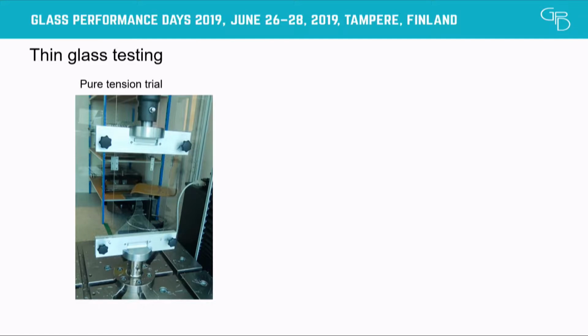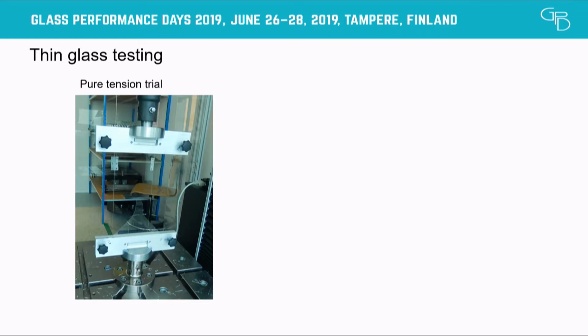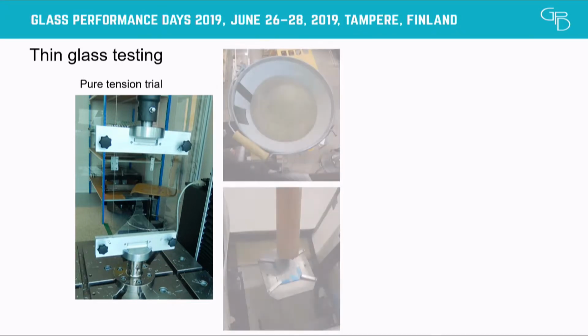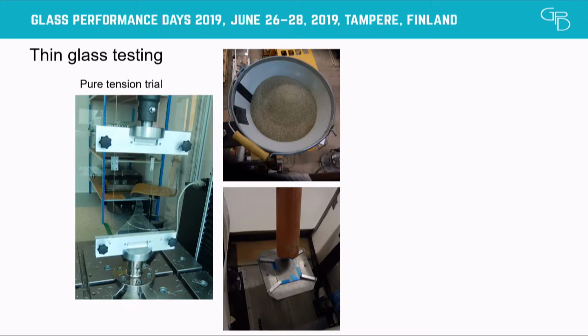I was a bit scared in the beginning because I had some time constraints. So I said, OK, let's order this glass. Then if it doesn't work in the pure tensile test, we can still apply the aluminum plates and see how the testing goes. It's tricky because clearly there are the edges of the glass and the edges on my slot where there could be some flaws which will trigger the fracture to occur. Oh, OK, you can still see it, no problem. That will occur on the top.